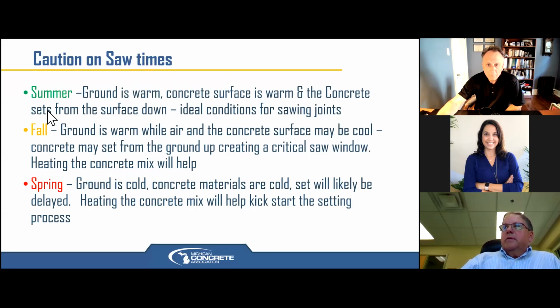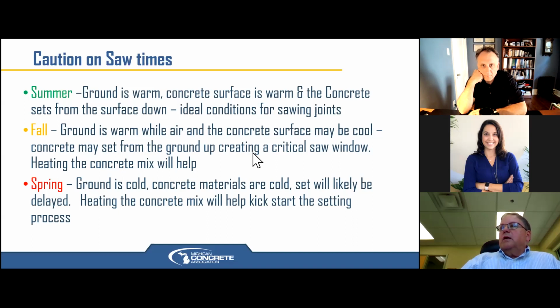So a couple of things on saw time. In the summer, the ground is warm, the concrete surface is warm, the concrete sets from the surface down. Ideal conditions for sawing joints, right? The top of the concrete's going to get hard fast, and we can saw the joints, and then we're in good shape. But in the fall, the ground is still warm while the air temperature really cools off at night. With the surface temperature of your concrete being cool, the concrete may actually start setting from the ground up, creating a saw window issue.